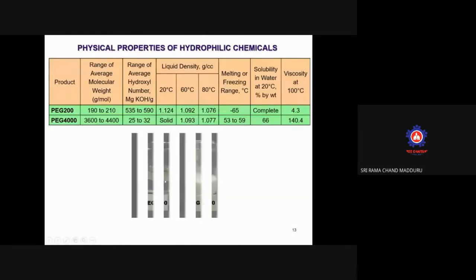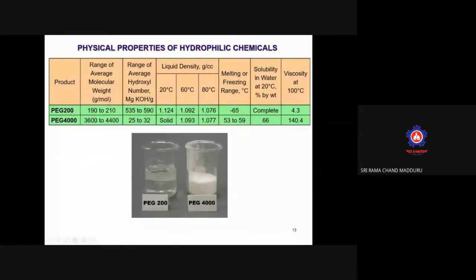Here you can see PEG 200, which is in liquid form, low molecular weight. PEG 4000 is higher molecular weight. There are different polyethylene glycols with varying molecular weights available: 200, 400, 600. According to the change in the molecular weight, the percentage of addition in the concrete changes. At room temperature, PEG 200 is in liquid form, whereas PEG 4000 is in solid form.